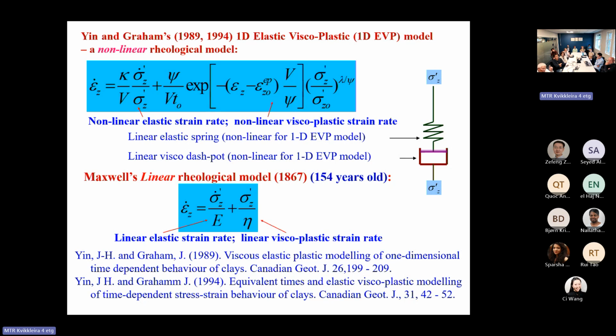Cyclic loading, I consider, okay, you can see my explanation. The creep is mainly due to water absorbed on clay particles. On static loading, maybe there is unloading only one or two very simple cycles. But on cyclic loading, I believe that's another factor we have to consider. You know why? Because with cyclic loading, you can load more frequently. You can change the particle orientation and sliding, which makes the particles get closer and closer.